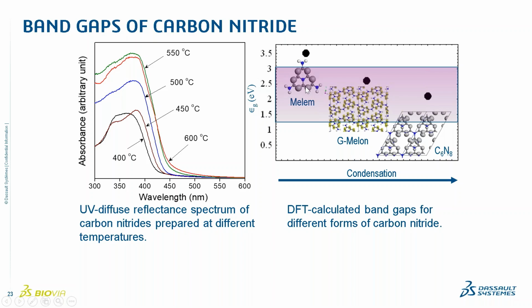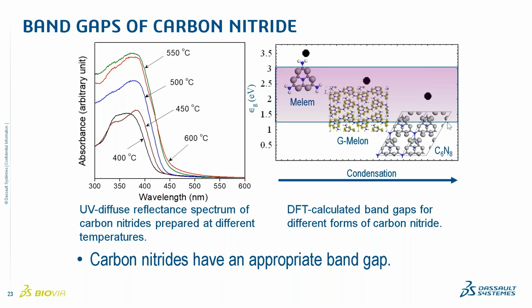We can also see this in simulations, that the more condensed, so for the Melem molecule, the HOMO-LUMO gap is quite large, outside of the band gap. As we are condensing further into this so-called melon or the sheet-like structure, we see that the band gap decreases as the electrons in the conduction band become more and more delocalized. So we can identify this trend that we could optimize the band gap here by letting this condensation path go to the appropriate level. So we see here that these materials have an appropriate band gap for photocatalysis.